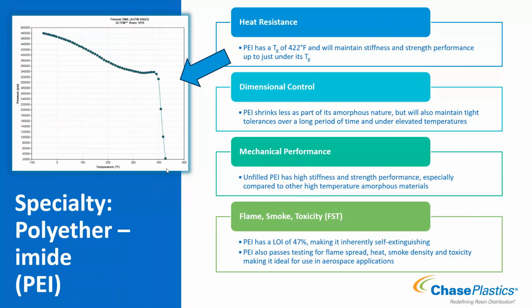And then lastly, the big thing that's utilized pretty commonly for applications is what we call FST - flame, smoke, and toxicity. In aerospace applications, we care about flame spread. We want to make sure it doesn't continue to burn for a long period of time, or really at all if we can help it. PEI has an LOI of 47. PEEK was self-extinguishing at 35, PEI is also self-extinguishing, but at 47. So you need quite a bit of oxygen, about double what we have in our standard air, before it will continue to burn. So it's self-extinguishing, it meets those flame spread requirements.